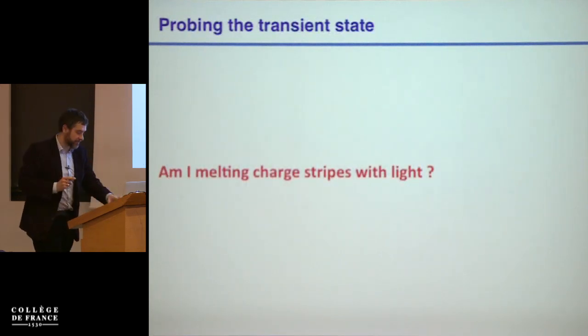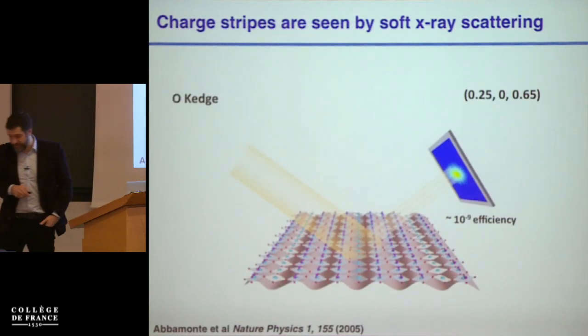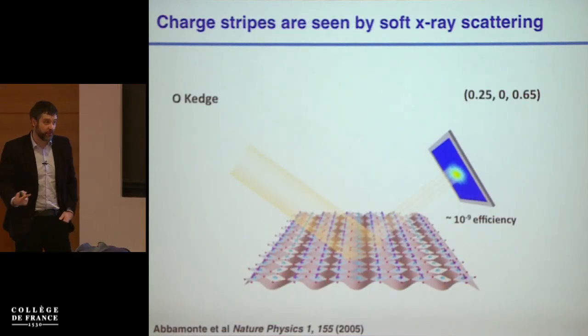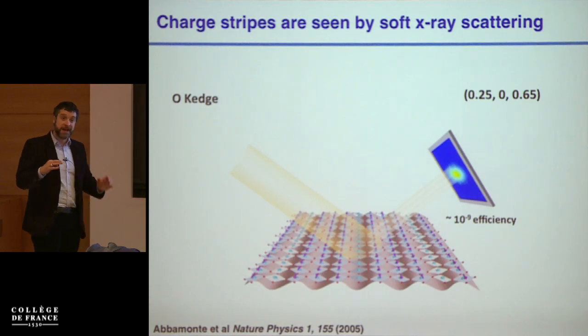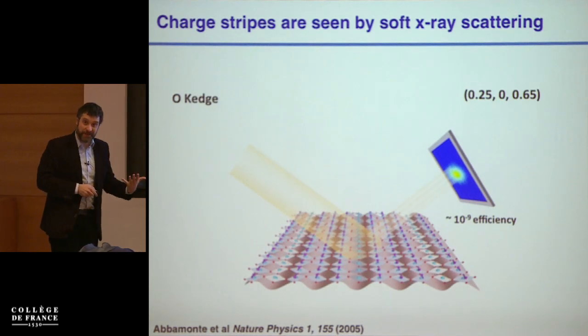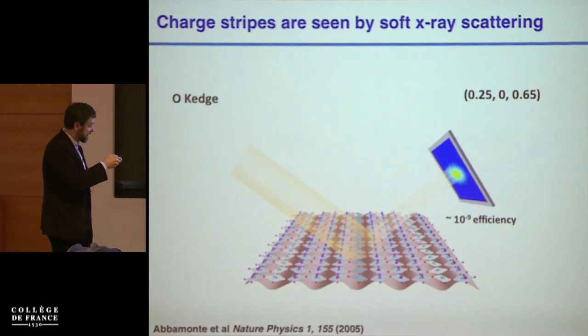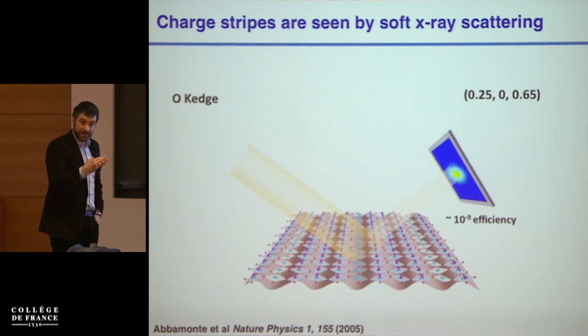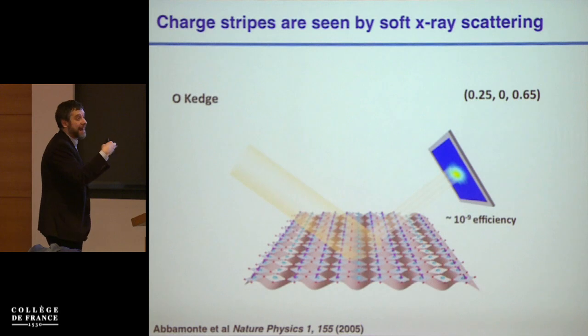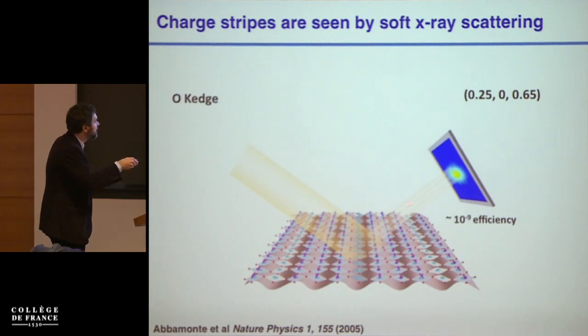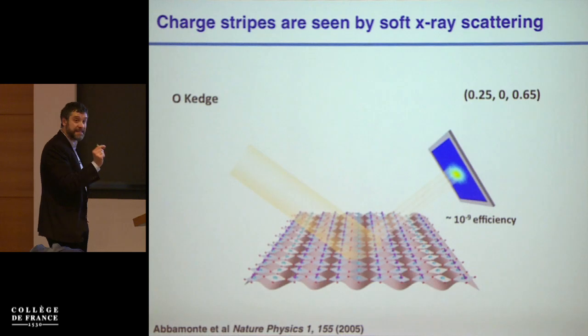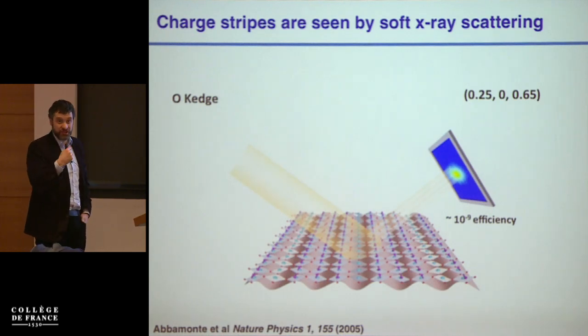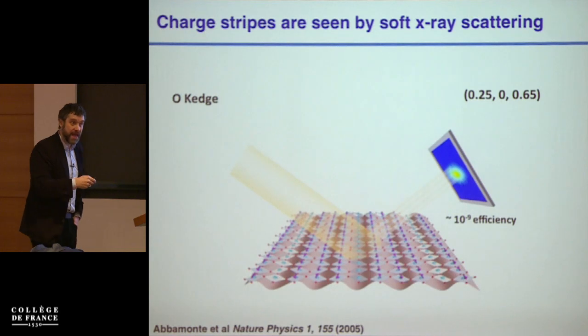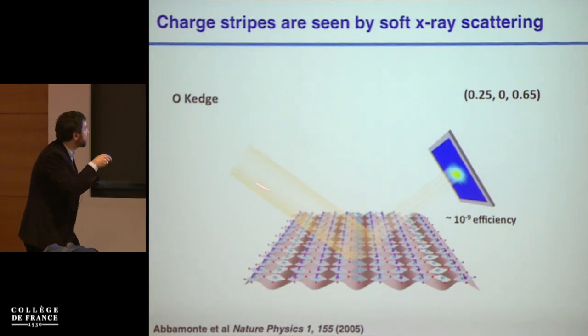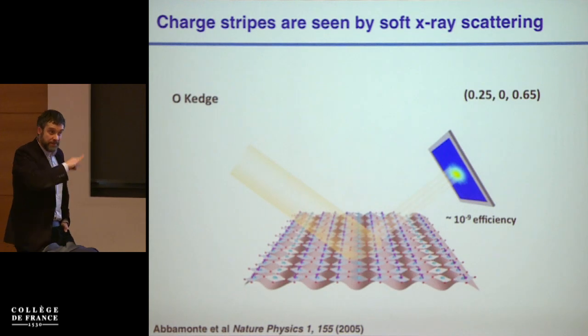Am I really melting stripes with light? The way one does this is, remember, I told you before about experiments with free electron lasers. If I use free electron lasers, I can measure the lattice positions. But what I can also do is to try to look at charge and spin order. I can do this by measuring diffraction in the soft X-rays, looking at superlattice peaks that are indicative of order that develops in the plane. I can do this if I go resonant either with the oxygen K edge, or with the copper L edge. I can look at some superlattice peak that is indicative of the appearance of stripe order.